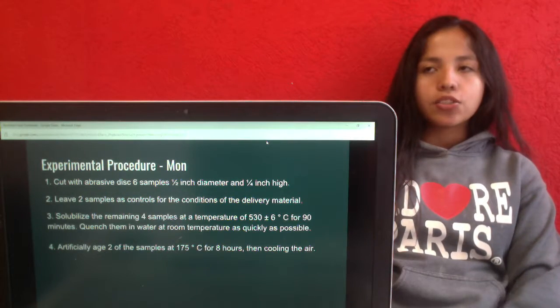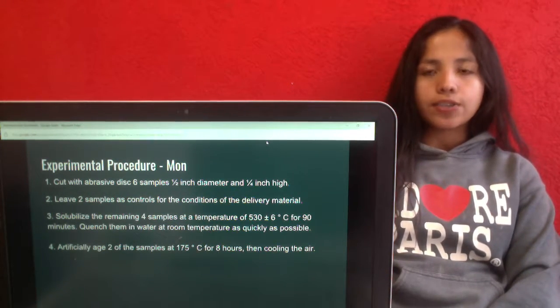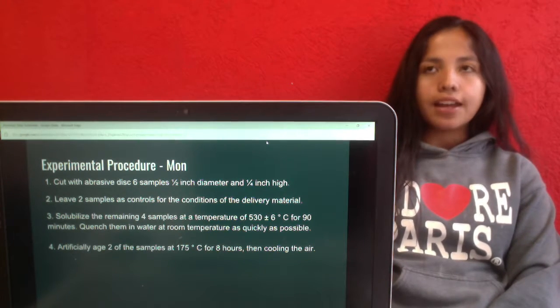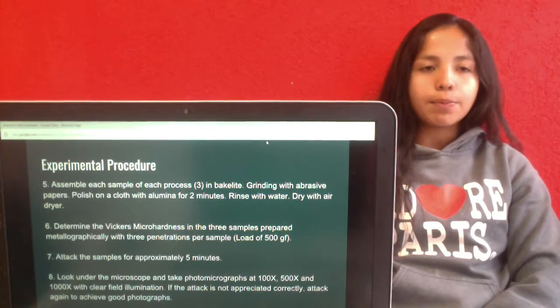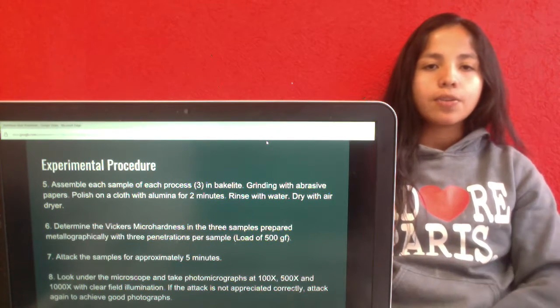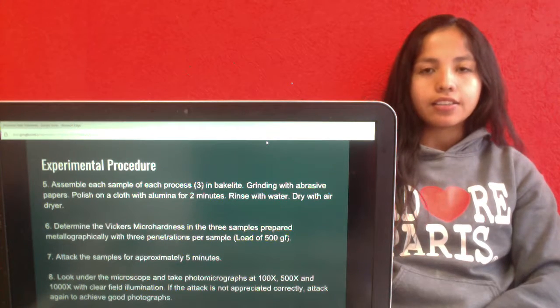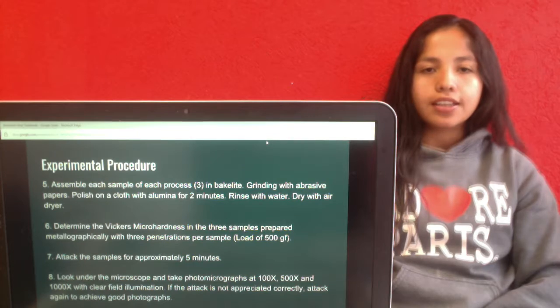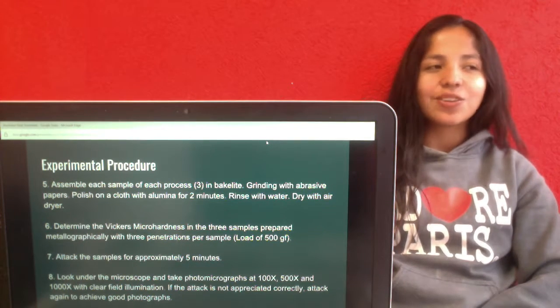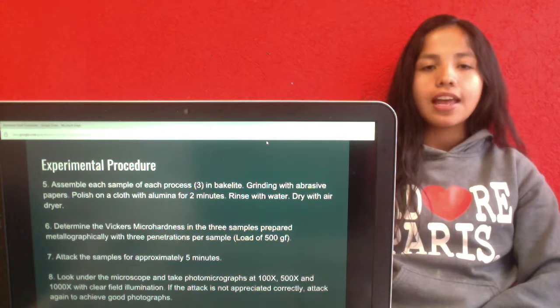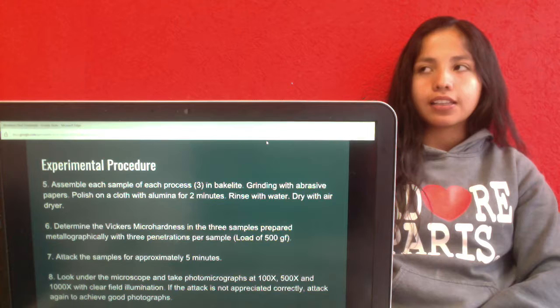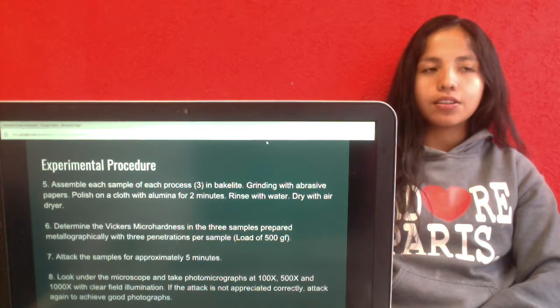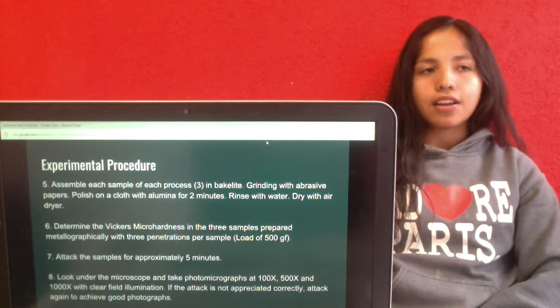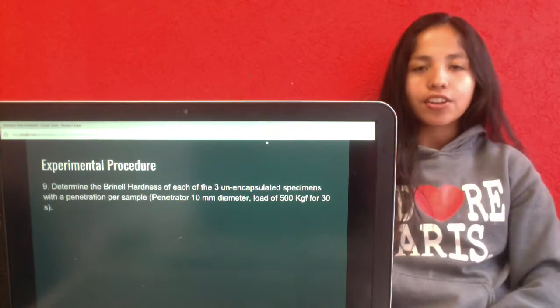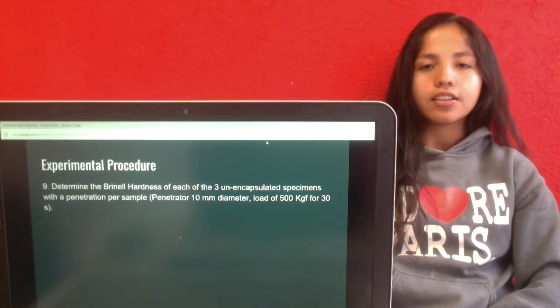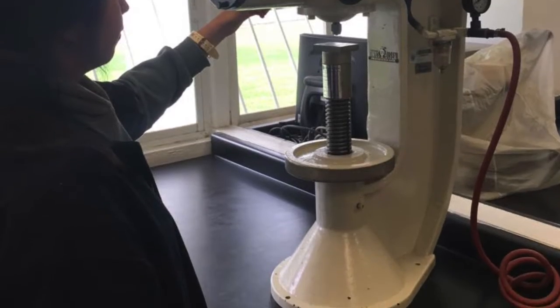2 of them we introduce again into the muffle, but at 175 degrees for 8 hours, and we cool them with air. 1 sample of each different treatment, we mount in bakelite, and we grind it with the abrasive papers and polish them with alumina. We determine the Vickers microhardness in the samples, and then we attack them for approximately 5 minutes, and we look at them under the microscope and count the grains in them. For the other 3 samples that were not encapsulated, we do the Brinell hardness test.